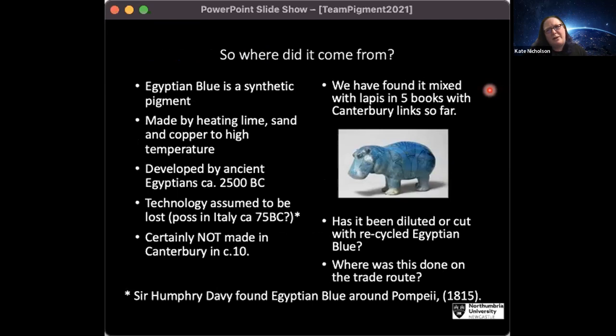Why is this unusual and where did it come from? Well, Egyptian blue is the first synthetic pigment known to humanity, made by heating lime, sand, and copper to a high temperature. The technology was developed by the ancient Egyptians around 2500 BC. There are many examples of Egyptian artwork containing this pigment. The technology was assumed to be lost, possibly in Italy around 75 BC. It's certainly not being made in 10th century Canterbury.